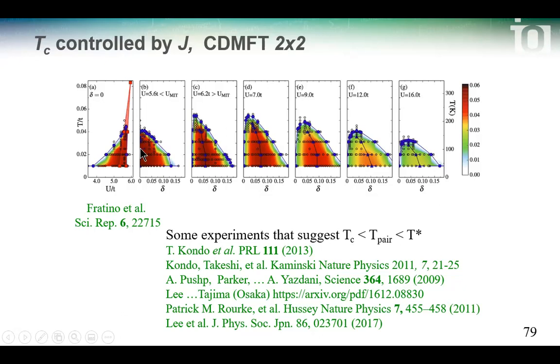Another question is whether this model agrees with the pressure dependence of Tc. Yes, it does, because if you apply pressure on the hole-doped cuprates, then Tc increases. Applying pressure means increasing the hopping between unit cells, which means that t goes up, and if t goes up, J goes up.